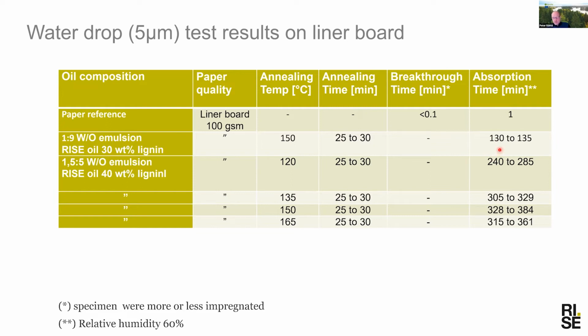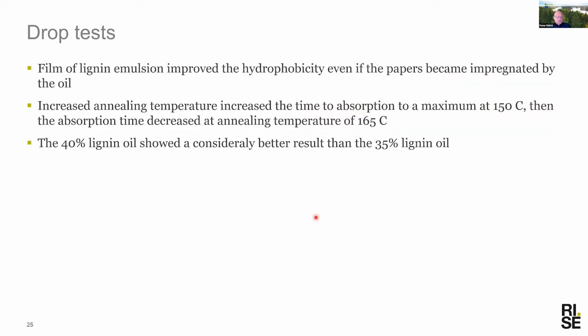We also can see that when we increase the annealing temperature, we increase the time for absorption up to a point of 150 degrees. Above this, we probably destroy the structure a little bit. So that is kind of what we see in this slide.